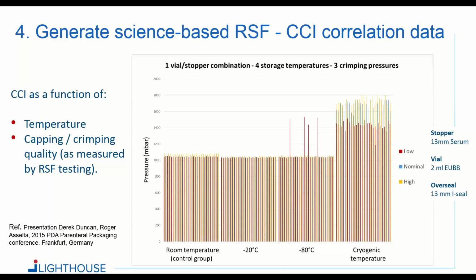So here you can make a risk assessment. Do I want to use this vial stopper combination, but make sure that I am robustly capping and crimping my vials? Once you get to cryo temperatures, then you see very high failure rates. And in fact, at the low or the loosely capped and crimped vials, everything fails. And you see, I believe, just a few of the vials at the high and nominal capped values holding closure, but everything else failing. So clearly you would not want to use this vial combination if you're going to go down to cryo temperatures. So again, very robust science-based data that gives you very good insight, not only into the primary packaging components, but also to how that correlates to vial sealing.